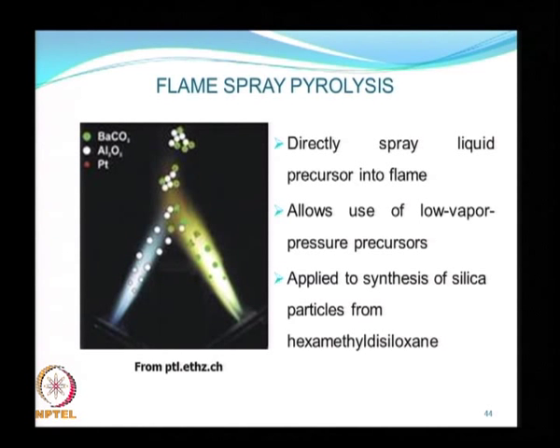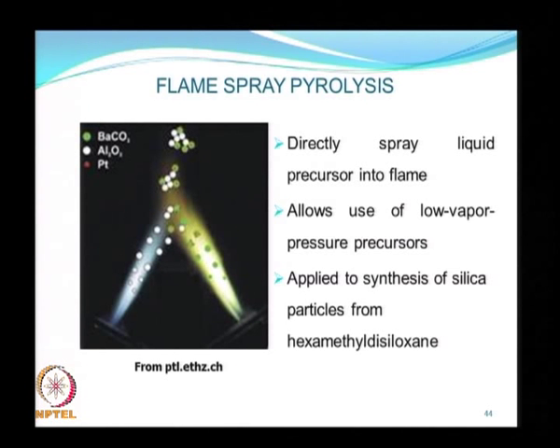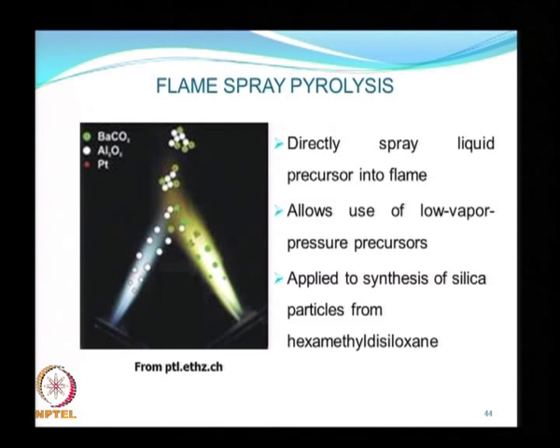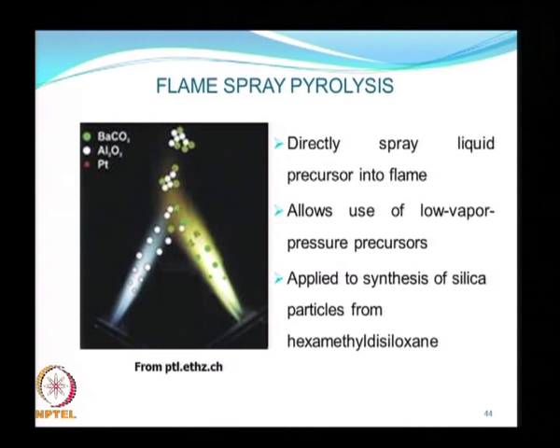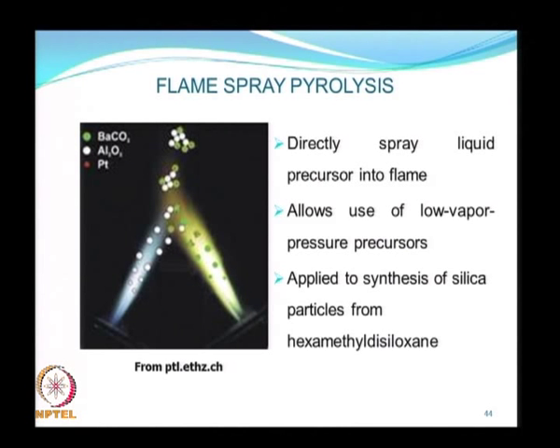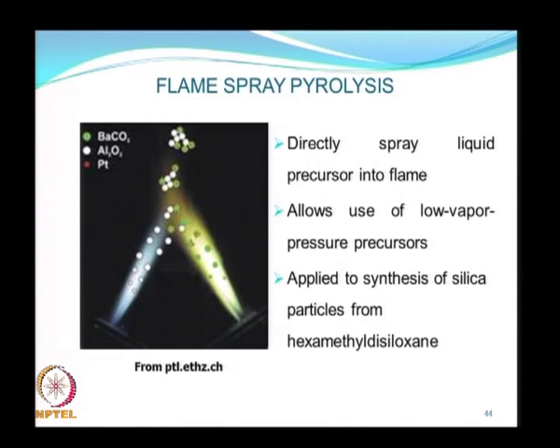Flame spray pyrolysis is a combination of flame pyrolysis and spray pyrolysis: liquid precursors are injected directly into the flame. The advantage is that low vapor pressure precursors can be used, because the combustion process supplies sufficient heat to vaporize even low vapor pressure materials. This method is applied to the synthesis of silica particles.